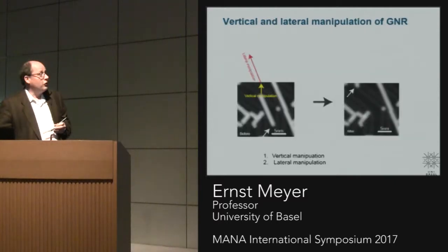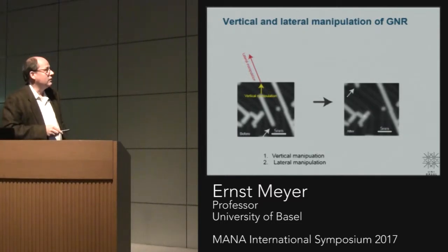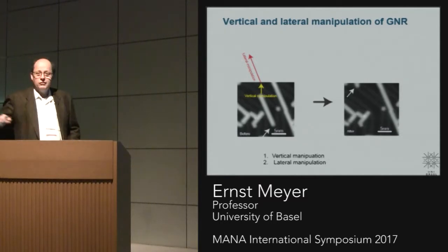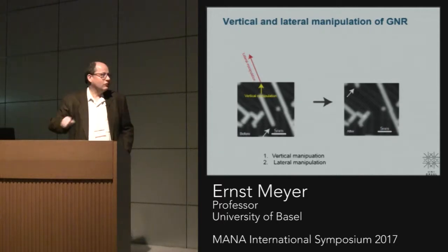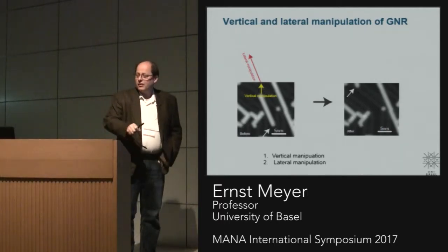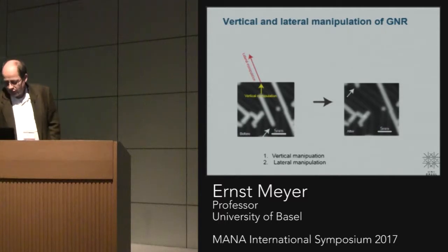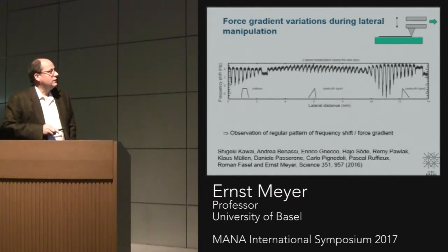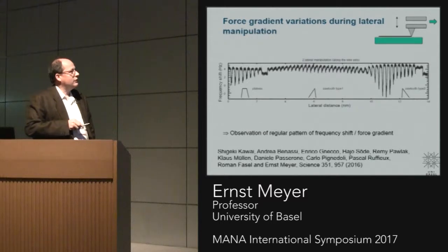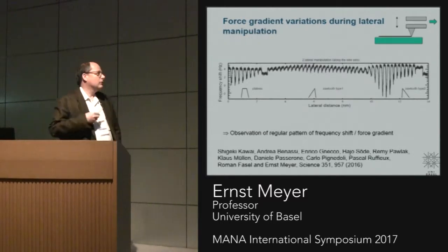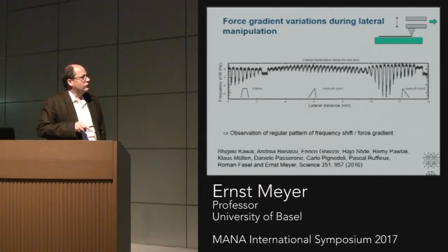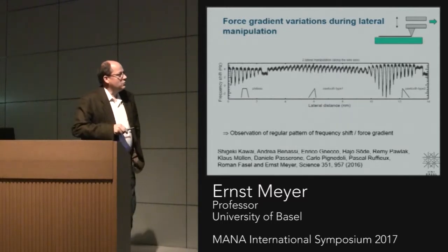Okay, so we can do further experiments. So you can really pick up again one of the ribbons, move up a little bit vertically and then horizontally. So you really, like a sled on the snow or something, you pull it along the surface. And then you can measure simultaneously the forces, and there you see some oscillatory behavior here. They're very weak again, so not very large forces, but they also show here this sort of a beating pattern. You see it sort of increases here in this area, and then has some minima here.